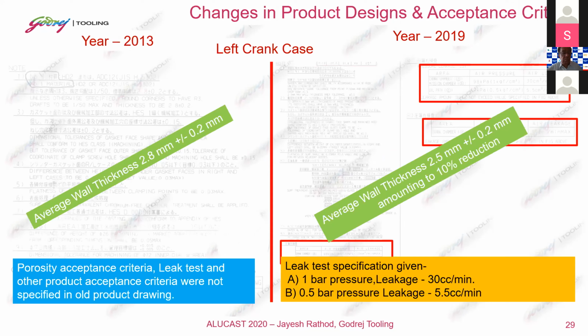I drilled down further into how this engine weight can be reduced. When we look at the average wall thickness of a two-wheeler transmission component, it was 2.8 plus minus 0.2, the tolerance given in 2013. Now it has come down to 2.5, around a 10% reduction in section thickness. So you can imagine what the total weight reduction will be with respect to this.